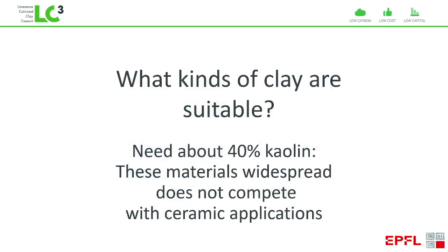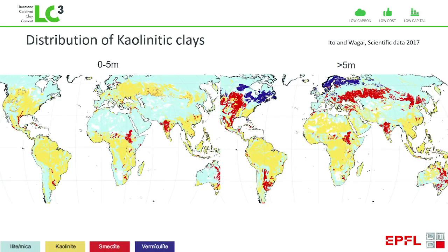So our first issue was to find the right kind of clay. We don't need very high purity materials. We can use materials with just around 40% kaolin, and these materials are very widely distributed worldwide. Everywhere you can see this kind of yellow color, you will have suitable materials for making this calcined clay. And you can see this is particularly good in the developing countries where the demand will be strongest in the coming decades, but also in Europe we have some quite good areas.